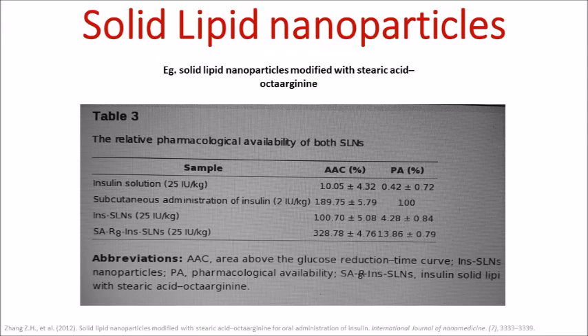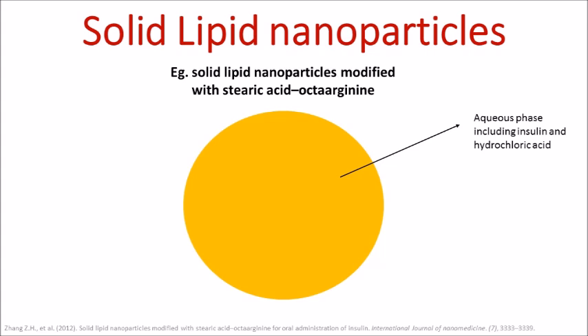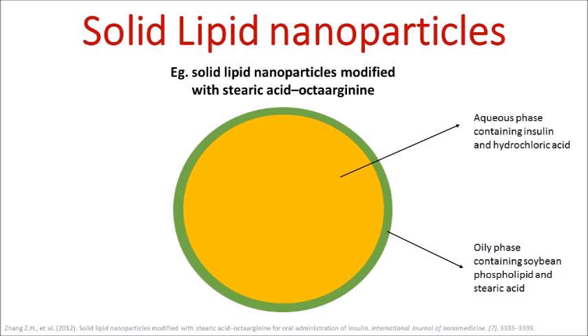The emulsion solvent diffusion method is used in the preparation of solid lipid nanoparticles modified by stearic acid octaarginine. Insulin is dissolved in 0.1 molar hydrochloric acid, which forms the inner aqueous phase, and this phase has a significant effect on the entrapment efficiency of insulin. Then acetone solution containing stearic acid and soybean phospholipids is added to form the oily phase. The resulting mixtures are dispersed for 15 seconds, leading to a water-in-oil emulsion. The oily phase affects the size distribution of the insulin solid lipid nanoparticles.